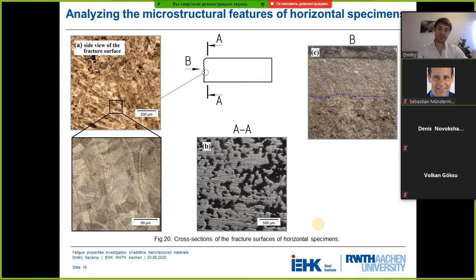Now we come to horizontal specimens, and on the side view of the fracture surface we see the morphology of equiaxed grains. And since the crack propagated perpendicular to the columnar grains, the transverse fracture surface was formed. In this case, the crack propagated through longer routes, deviating and being hindered by the columnar grains. So that caused the longer crack propagation. With regards to the microstructure, these specimens experienced a longer time interval, higher temperature gradient, and therefore high cooling rates. That resulted in a smaller diameter of the porosity, which was distributed perpendicular to the columnar grains. So all of these features resulted in the slowest crack propagation.